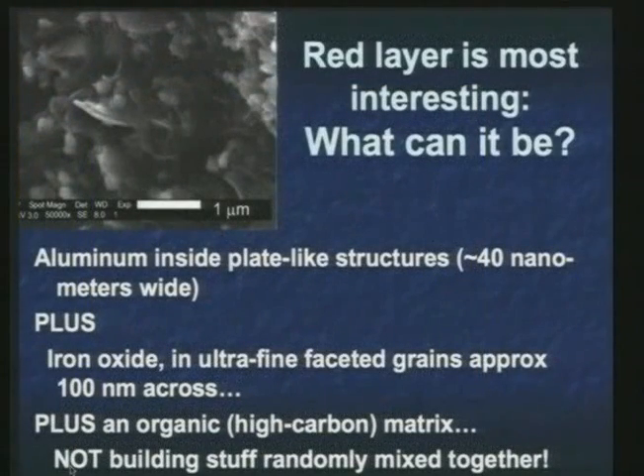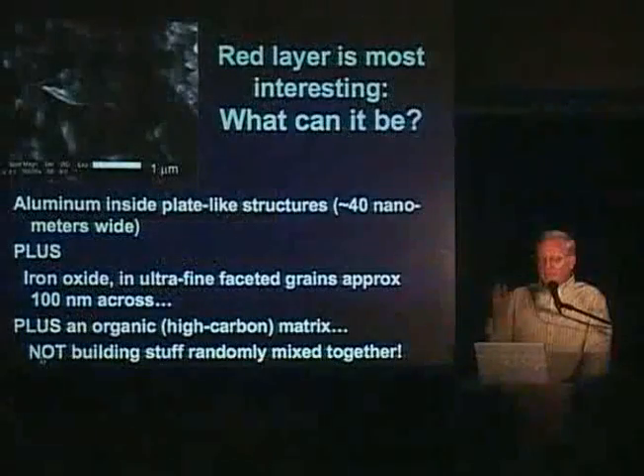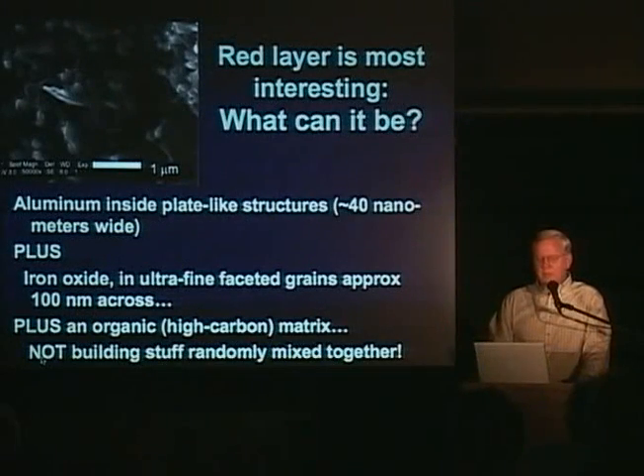Now, this red material is most interesting to us because it has aluminum inside these plate-like structures. The plate-like structures are quite uniform in thickness from what we can observe with the scanning electron microscope, 40 nanometers wide. Plus, the iron oxide appears in these ultrafine faceted grains, approximately 100 nanometers across, and again, very uniform.